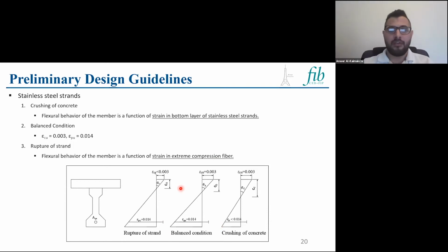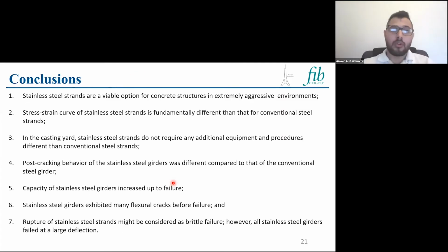deflection. If we choose our member to fail due to rupture of the strand, then the flexural behavior of the member is a function of the strain in the extreme compression fiber. The higher, the better, because if we have this value high, then our curvature is high, the deflection is high, and also the compression force from the concrete is high. So in conclusion, stainless steel are now a viable option for concrete structures in extremely aggressive environment.